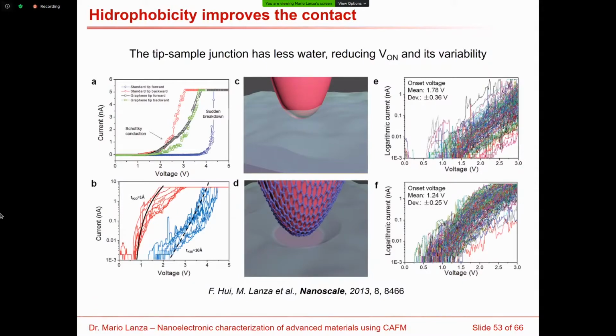So basically this means there was a dielectric there and we broke it. Even if it was only silicon, which is not insulating, it behaves as an insulator. When we perform the same study with graphene-coated tips, we observe overlap of the forward and backward curves, which moreover show a current trend that is similar to what is expected in a metal-silicon junction.